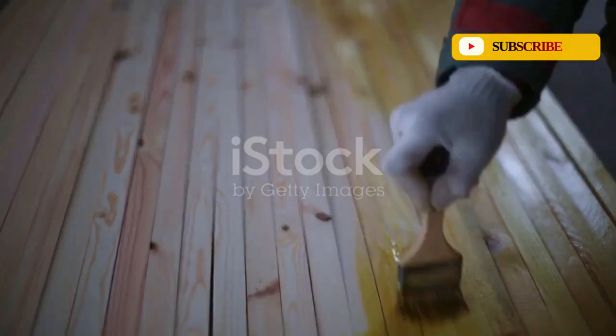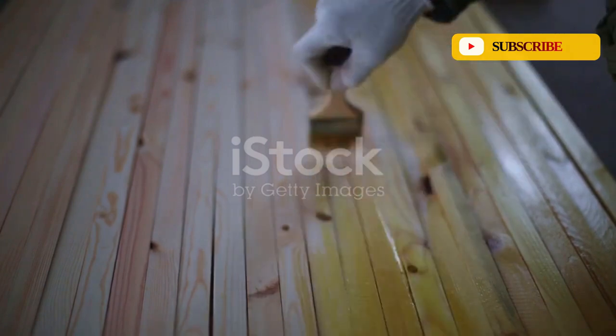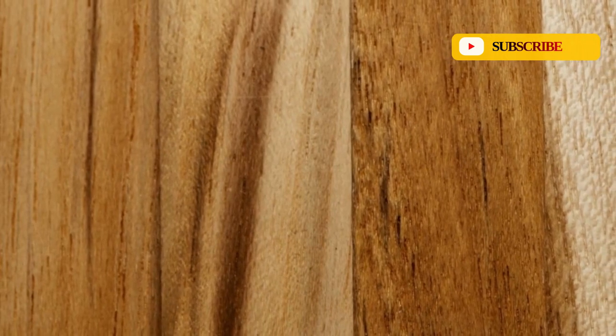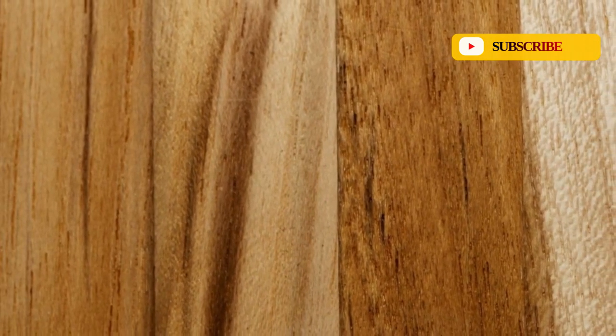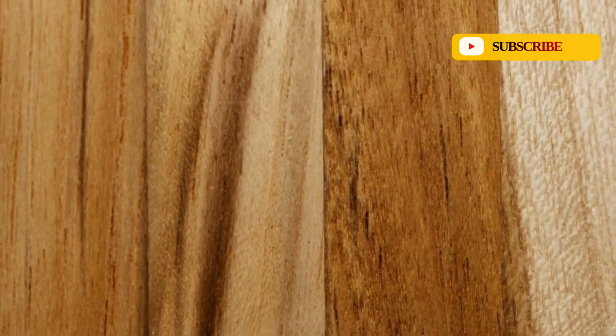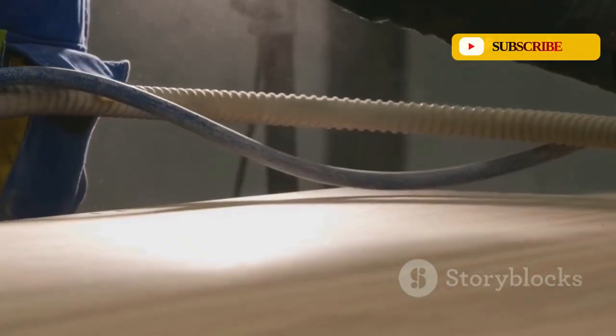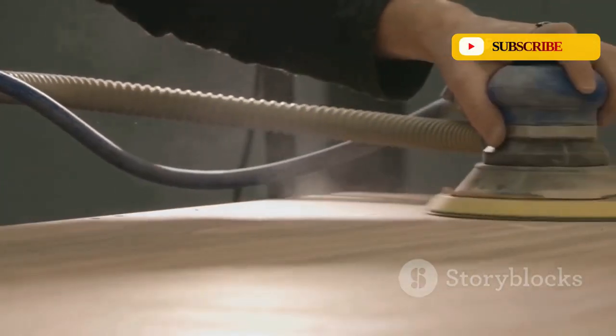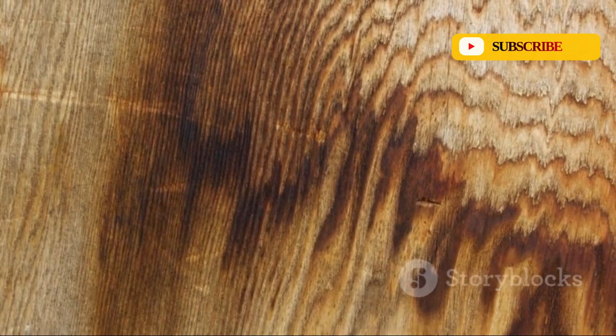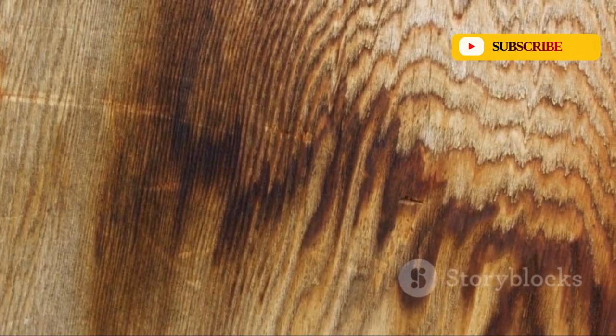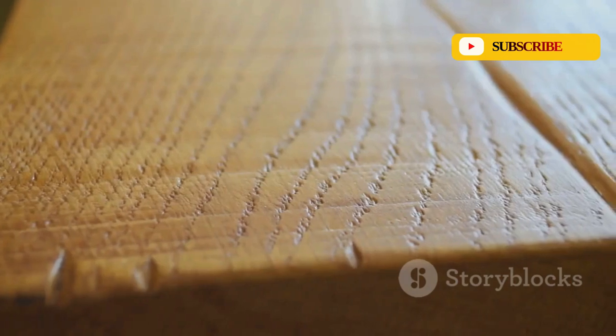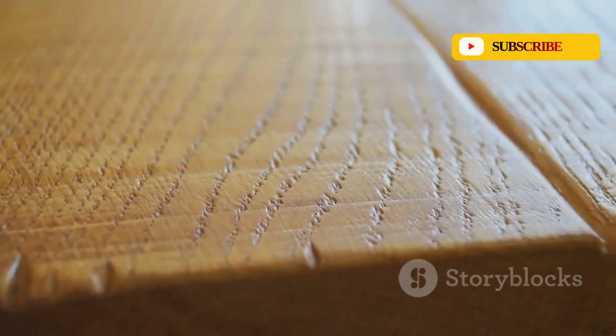A polyurethane finish, over months and years of use, tends to yellow and become brittle. Scratches stand out as white gouges in the plastic layer, and as we've seen, it is prone to peeling and clouding. The wood underneath is frozen in time, unable to develop the rich depth and character that comes with age. My oiled walnut, on the other hand, has only gotten more beautiful. The finish has deepened the wood's natural color, and the grain seems to have more life and iridescence. It's developing a patina, an honest record of its use.